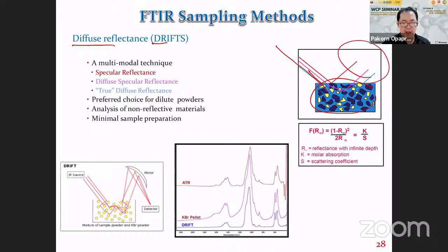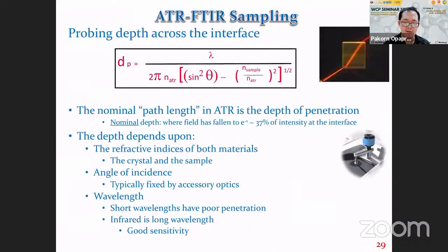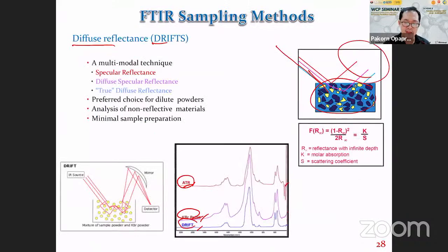So, these are examples of spectra of the same material, measured from different techniques. The top one is ATR. The middle one is transmission, and the bottom one is from the DRIFT technique. And you can see, even though these come from the same sample, the relative intensities are slightly different. This is because of the different nature of the measurement.